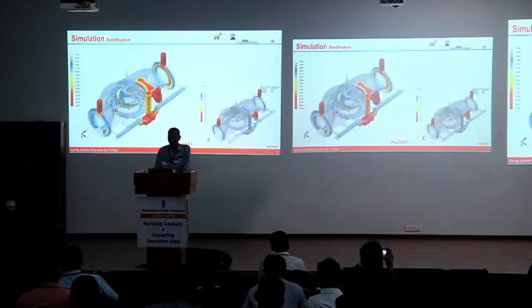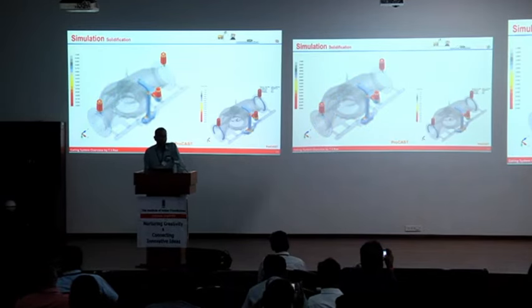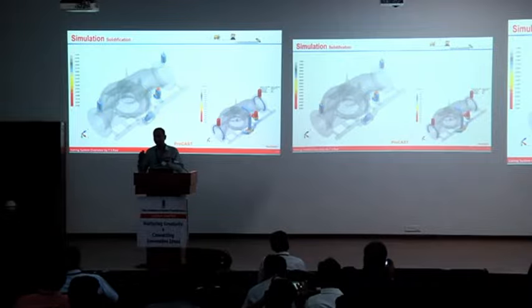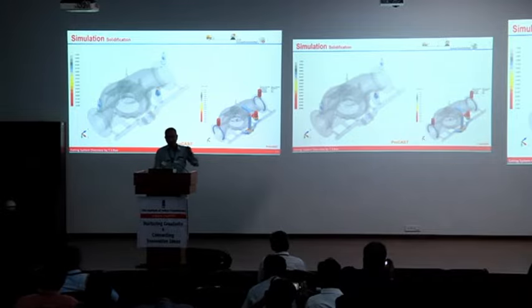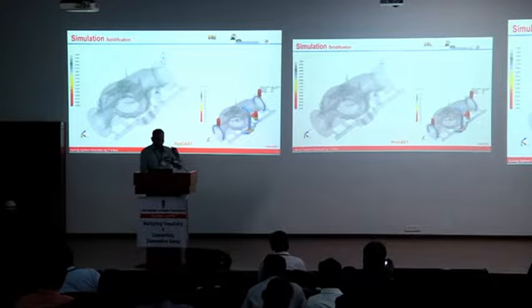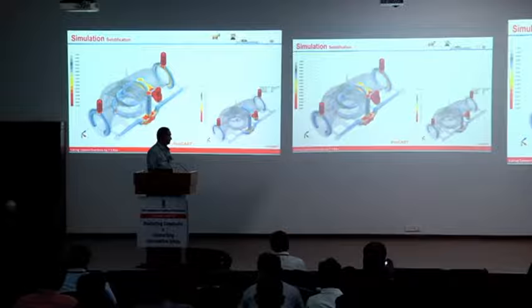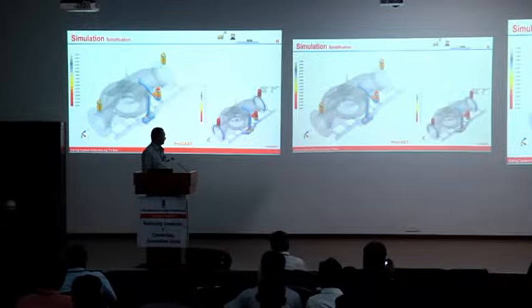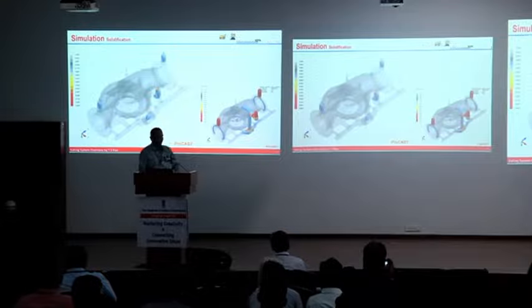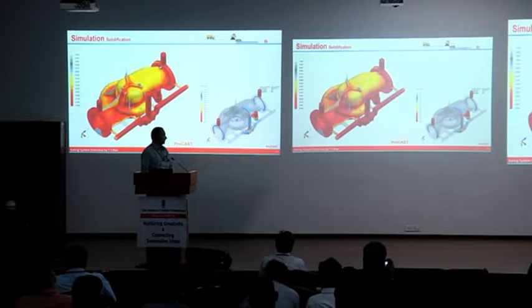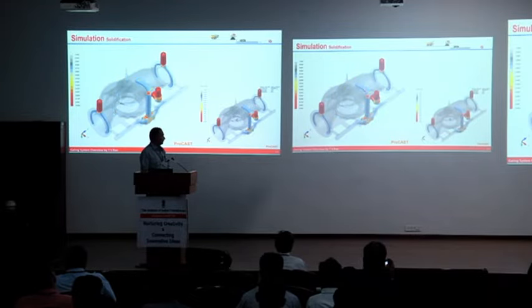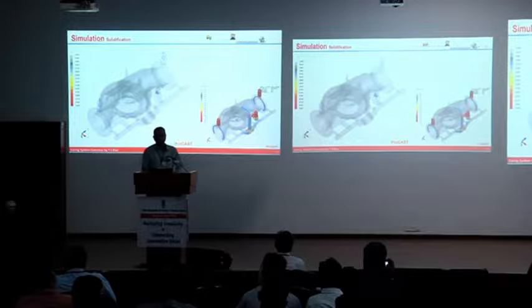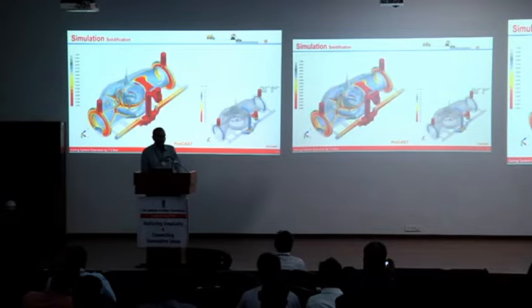The next one is the solidification. This is also called directional solidification. Here you can find out how the casting gets solidified. We know the thin wall starts solidifying first, and where the chill is connected, because the chill is conductive, you can see it solidifies first. Then comes the directional solidification, and we can also see the isolated spots in the casting cavity. Wherever it is solidifying last, if it is not connected to the feeder, we end up with a shrinkage here. Similarly here, if the isolated spots in the casting are not connected to the riser, we end up with a shrinkage.